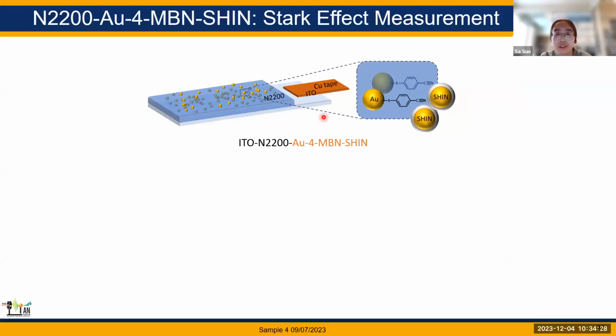So this is our electrode configuration. We basically have N2200 spin coated on the ITO and deposited with gold. Further, the gold is functionalized with a benchmark vibrational Stark shift probe molecule 4MBN, which has a nitrile over here as the electric field probe. And then we deposit SHINs particles. SHINs stands for shell isolated nanoparticles, which are basically used to enhance the 4MBN signal to be seen from the Raman spectrum. So the 4MBN is a Stark effect probe to measure the electric field and thus measure the gold Fermi level.